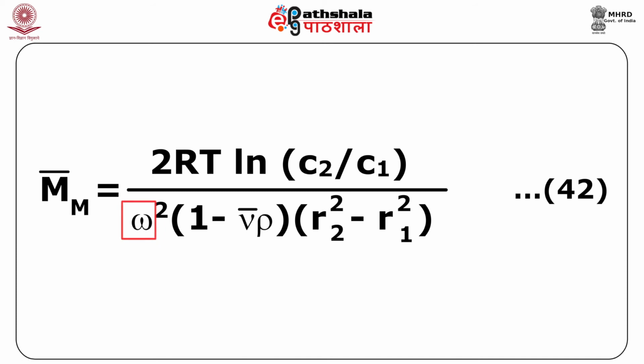of the rotor in radians per second, ρ is the density of the solution, C1 is the concentration at a distance R1 and C2 is the concentration at a distance R2 from the axis. The concentration ratio C2 by C1 is determined by the photometric measurement. From equation 42, we see that a plot of ln C versus r² should be linear with slope equal to M bar ω² (1 − ρ V bar) divided by 2RT. Thus, from the measurement of the slope, M bar can be calculated.